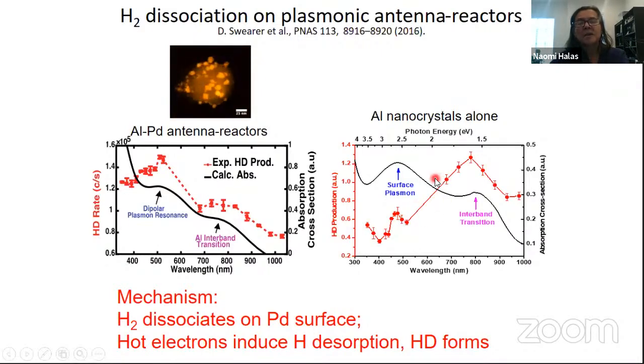But what's also really interesting, if we look at the data for the antenna reactor, the wavelength dependence is completely different. And now it turns out that the plasmon controls the process, not the interband transition of the aluminum. So what's going on here? Many of you might know a bit about palladium. Of course, it's a very well-known catalytic material, but also its interaction with hydrogen is very well known. Hydrogen dissociates spontaneously on a palladium surface. So what could be going on to make this H2 reaction so much more active on this antenna reactor?